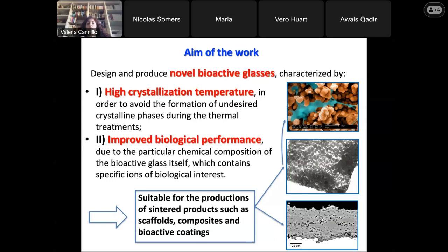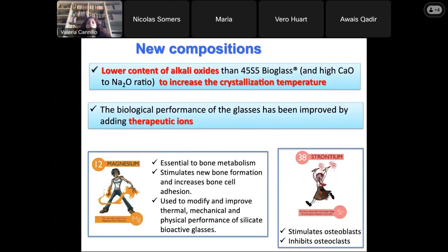Thanks to this combination of properties, such bioactive glasses are so suitable for the production of sintered products, such as scaffolds, composites, or bioactive coatings. So, the new compositions are characterized by a lower content of alkali oxides with respect to 45S5, and this was done to increase the crystallization temperature.